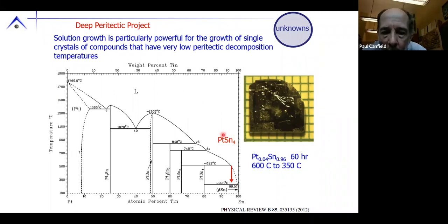So how would I grow platinum 2 tin 3, okay, without all this other stuff? Well, I'd have to start with a composition that's more than 75% tin, okay? Then I have a homogeneous liquid. I start growing my platinum 2 tin 3. I cool down, and I better stop the growth before I cool below 745. Okay, how do I stop the growth? Well, I yank the crystals out of the liquid, or I remove the liquid from around the crystals, and that's what I tend to do. I have a filter, and I dump them into a centrifuge, decant, and get the crystals.